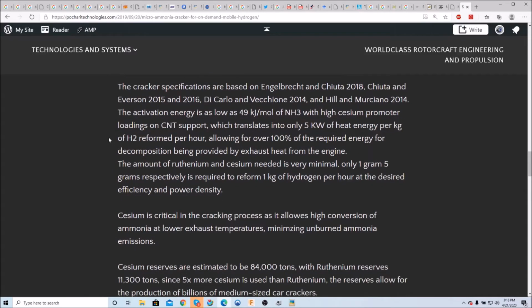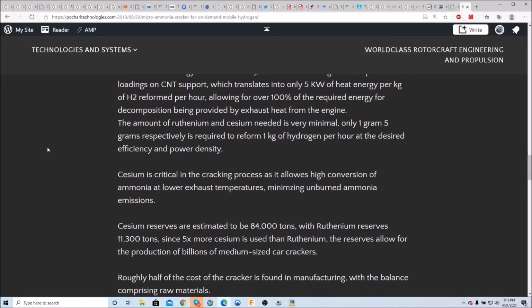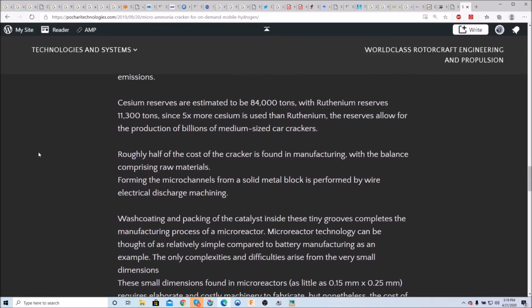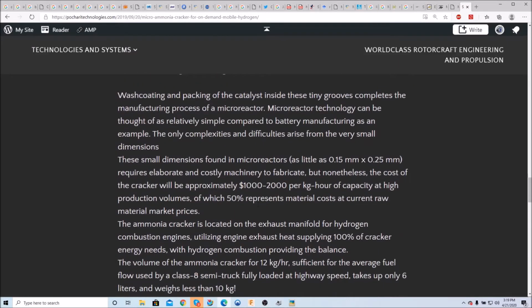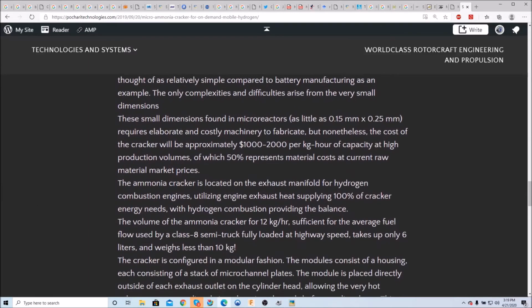Cracker specifications. Okay, Chiuta published a lot of work on crackers. Activation energy could be as low as 49 kilojoules per mole. Probably going to be more around 80. I've upped these numbers. Again, it really varies a lot, but the most important number is the amount of ruthenium needed. So I estimate around $1,000 to $2,000 per kilogram hour of capacity at high production volumes.